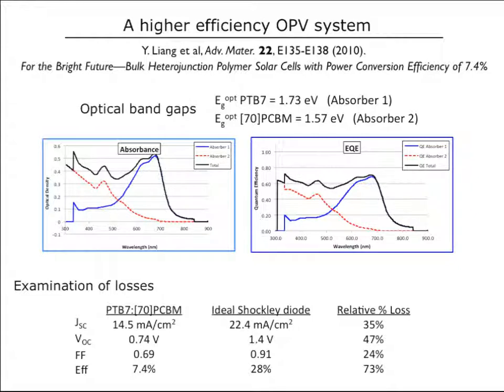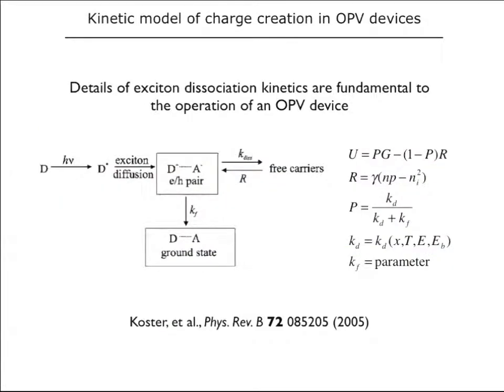So if we take a look at the individual characteristics, again, we have a current of 14 milliamps per centimeter squared. If we use an ideal Shockley diode equation, with that band gap of 1.6, we'd expect a current of about 22 milliamps. So we're losing about 35% in the current. VOC, 0.74. The ideal case would get about 1.4. Here you see a really big loss, about a 50% loss in the voltage. Fill factor, we're losing a little bit less, 24%. But in the end, we've lost 73% over the ideal diode equation. So I want to point out that the VOC is one of the biggest losses that we have to deal with. So how do we model that photophysics in a little more detail?